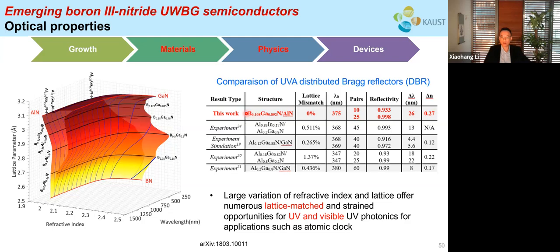And for instance, if we have the boron gallium nitride and aluminum nitride here, we have 0% lattice mismatch, and then we can achieve more than 90% reflectivity with 10 pairs and 25 pairs of superlattice, and with a large bandwidth as well. And this is a so-called DBR structure that is in every single semiconductor laser today. And in particular, this DBR will be very useful for applications such as atomic clocks because of the wavelengths in the UVA spectrum.